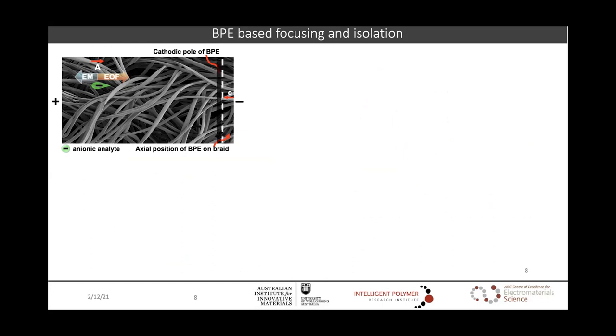However, when there is a BPE in the system, an ion depletion zone is formed, a zone that increases the electromigration due to the electric field gradient, high electric field gradients in this region. So the anionic solute moves towards its respective anode.